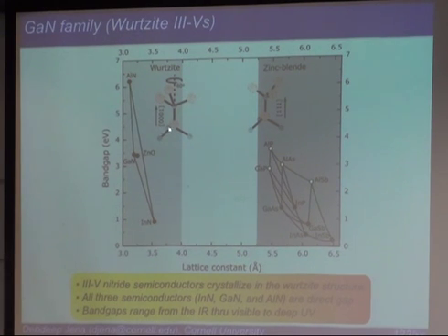Wurtzite is just slightly different. You go up, and there's a 60-degree rotation in the next step. So there is one tetrahedron like that. You go up, the next tetrahedron is not right on top, but it's just rotated by 60 degrees. Okay. So, did I say that right? Yeah, that's right. And that's kind of the major difference.